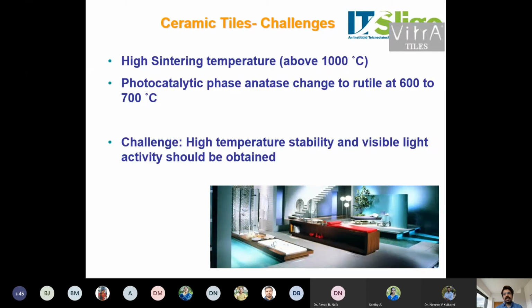So there are two challenges. One is obviously the visible light. You have to develop a TiO2 which works under the visible light. That's the first challenge. The second challenge is high temperature stability, because the photocatalytic phase, which is the anatase, doesn't have high temperature stability, which means it transforms to rutile at a temperature of 600 to 700 degrees Celsius.